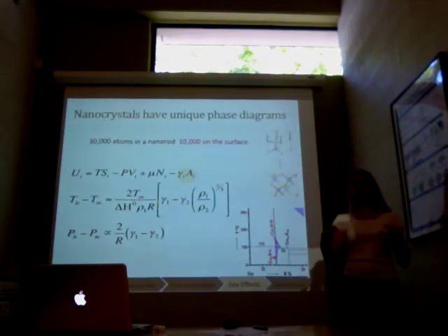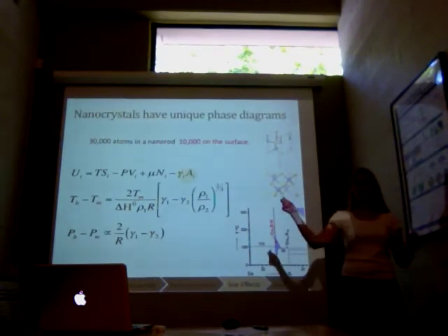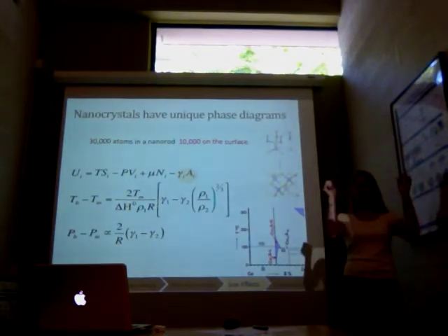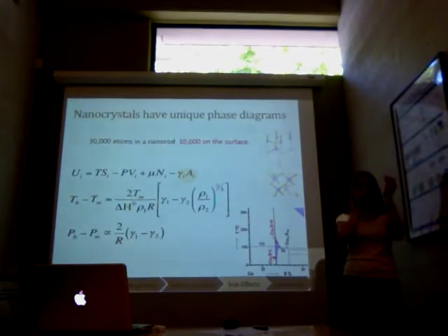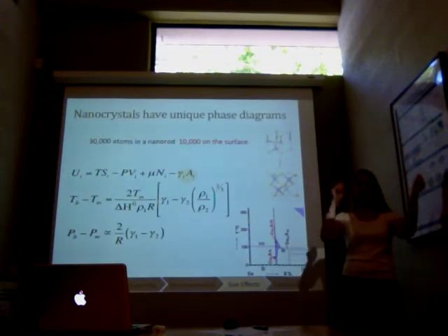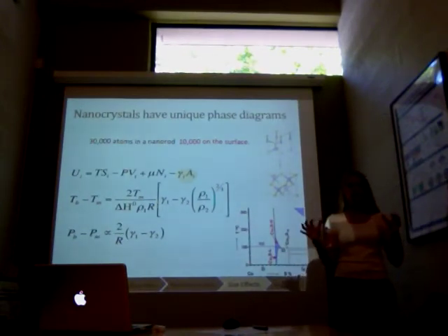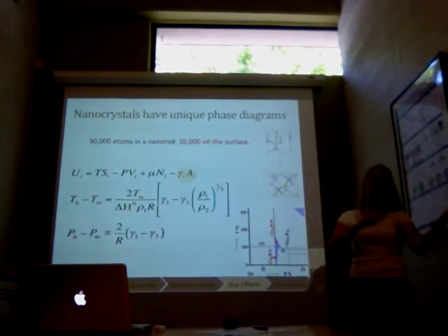After assembly, I would also take these films and dip them in a different ligand, hoping that that ligand would exchange out. And what happened was that if the ligand that I dipped it in was very short, then the nanorods, which are 4 nanometers in diameter with 2 nanometer rods, so we've got like a 50% aerial coverage, if you shrink those ligands, then all the nanorods lean a little bit, and it looks like grass that someone had a picnic on. You can see that there was some sort of order, and it makes nice patterns, but they all lean over quite a bit.